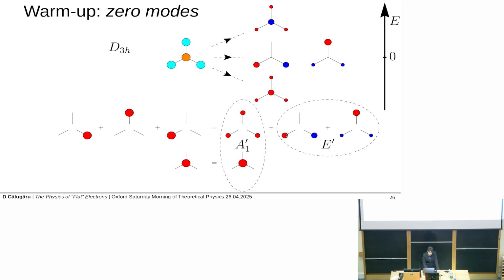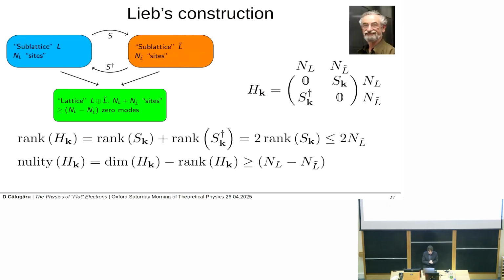On the other hand, I started with 3 orbitals, so I must have 3 after I hybridize them. These hybridized orbitals here that I'm denoting with E prime, which is just notation from group theory, really don't have the symmetry to hybridize with the central atom. So they will just stay here at 0 energy. Now, if you take this very simple picture and put it on a lattice, it turns out that this gives you the most general way of building flat bands in crystalline materials. And this is something called the Lieb lattice construction.